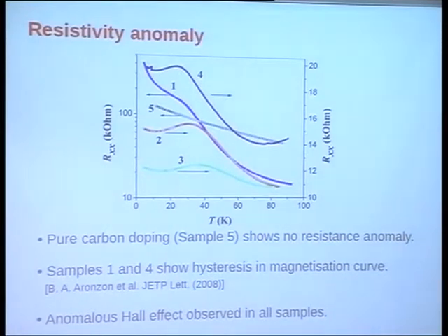I think the barrier is not that big in this case. So we estimated the tail of the wave function from the quantum well reaching out to the manganese layer, and assuming a certain thickness from the manganese layer, we found that the overlap is about 1%. Because the barrier is not that high there. In gallium arsenide devices, it's quite different. This would be a relatively big separation. So the quantum well acts like a probe. The quantum well has most of the holes, so it acts like a probe. We believe it's responding to the magnetization and its dynamics in the manganese layer. And delta means one single layer.